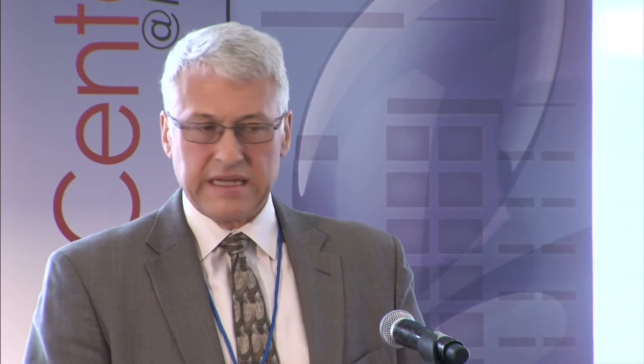Relative to this program, we realized a few new steps into a CMOS process flow. One interesting aspect was the realization that a BiCMOS-type technology is needed for high-speed device operation as opposed to just digital communications. The new materials represent a PECVD silicon waveguide for butt coupling into the germanium epi — also a new element — but everything else about the CMOS process was left intact. We leveraged quite a few existing processes including ion implantation for lightly doped drains for our bottom p-contact, as well as wet chemical treatments for cleaning surfaces for our waveguides and germanium structures.